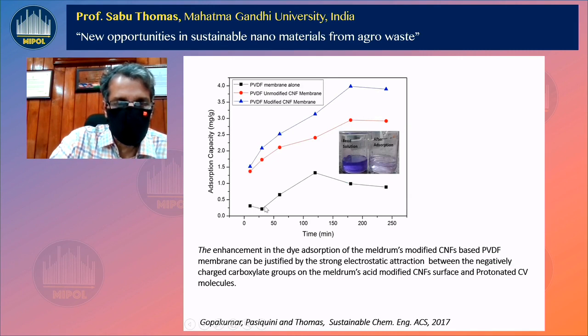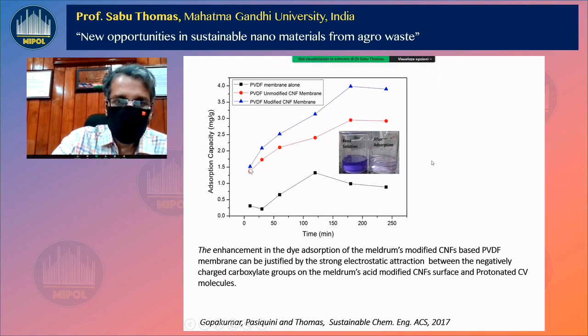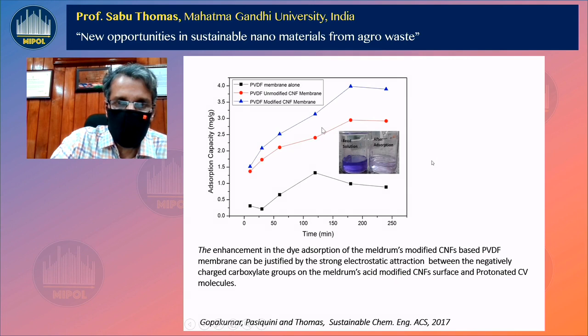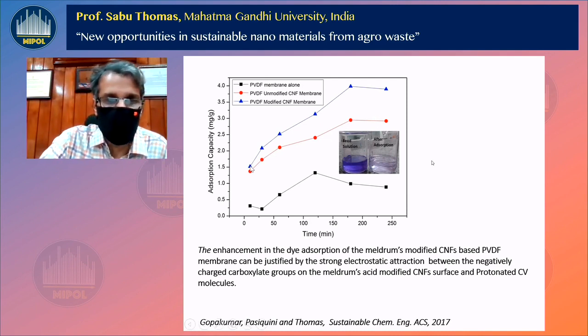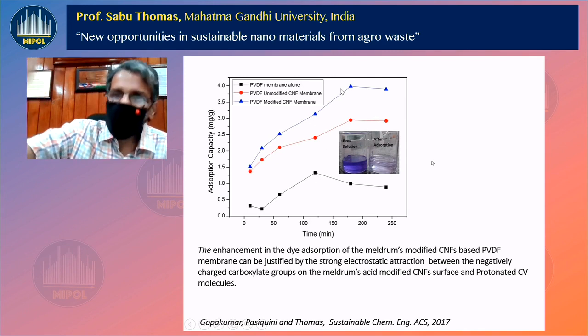And see the efficiency of separation. This is the normal commercial filter that you get from the market. Adsorption capacity as a function of time. You see the filter capacity is not very good. But if you give a coating with the nanocellulose, which is unmodified, no chemistry on the surface, of course, the separation efficiency has been increased. But if you use chemically modified nanocellulose, you see where we stand. We have something like 4 milligram per gram efficiency. The commercial filter is having something like 1.2. So you have a very good increase.